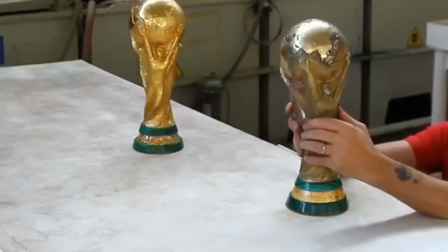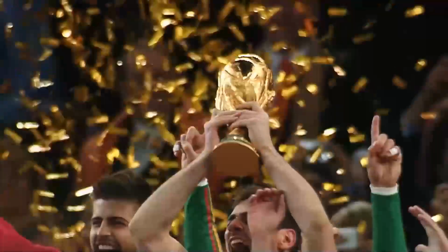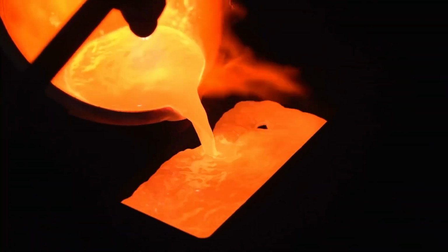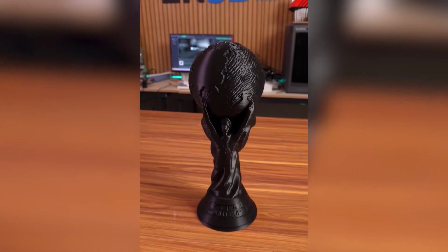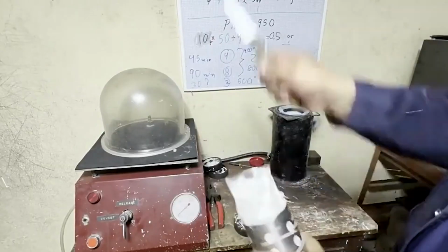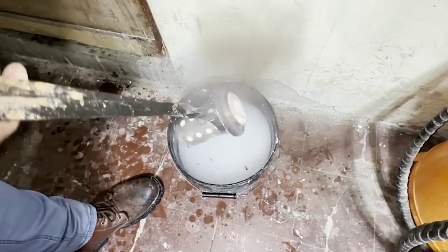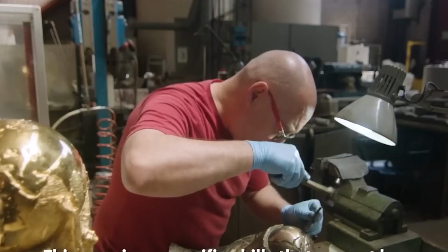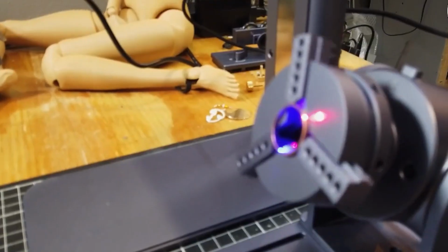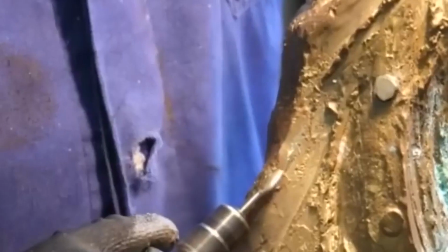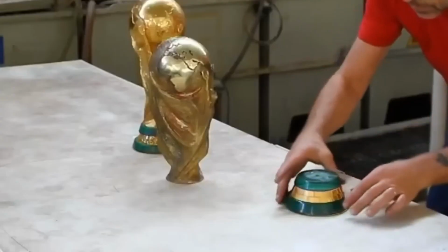Behind the raising of the trophy lies the melting of the gold, the removal of impurities, the making of the mold, the vacuum that pushes the metal, the thermal shock that reveals the piece, the filing that corrects imperfections, the laser welding that repairs pores, the polishing that transforms the surface, the malachite that completes the base, the engraving that preserves the memory, and the final inspection that ensures authenticity.